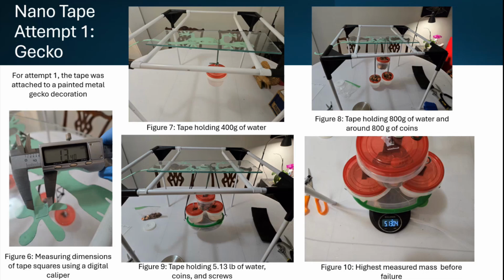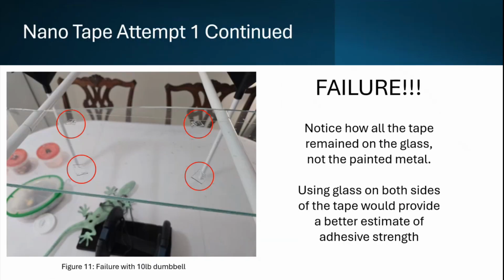So I realized that I needed to go a little bit higher in mass, so I went to 10 pounds, and it was a big failure. So at 10 pounds, the gecko fell from, or unadhered from, the tape, and you can see that in the bottom left. But it was important to note that the tape stuck onto the glass and it did not stick onto the metal, the painted metal. And this is evidence that it's not a good experiment to use this metal gecko. I need to use glass on glass contact to keep it relatively even between the two surfaces to make sure I'm measuring the tape, not the secondary material.